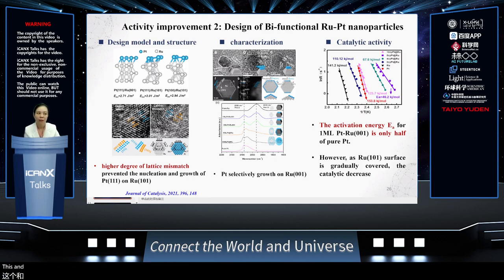This slide I want to show you is that we can use the inherent one as well. Here we do bifunctional ruthenium on the platinum nanoparticles. The good thing is that the surfaces with ruthenium and platinum, for certain faces, have a really good match, while for the other surfaces, they have a higher degree of lattice mismatch. So we utilize this kind of strain difference to obtain selective adsorption on certain faces, while leaving the other ones intact for the first few layers. And that gives us good enough performance, because after that, we obtain not only the core shells, but also the facet differences.